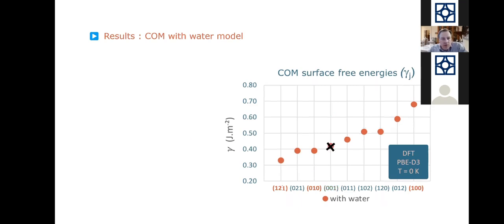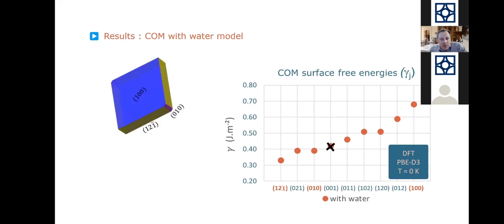And so let's now imagine, what happens if you delete, for example, one surface, one orientation, and you take it out of the equation? Then you will see that there will be directly a difference in the morphology. If we take away the 0, 0, 1 surface, then we will see that the morphology becomes more platelet-like. And this is what we want.